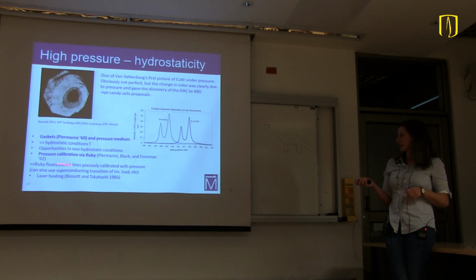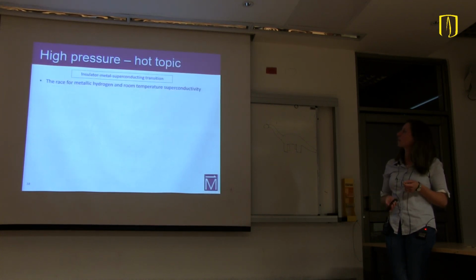And the next thing, also Piermarini and co-workers developed a way to measure the pressure inside the pressure cell by using the ruby fluorescence. So this is an example of a ruby fluorescence. When you shine a laser light on a ruby, it sends back fluorescence lines, and those lines are perfectly calibrated in pressure, so they shift in wavelength with pressure. So that was an absolute revolution for measuring the pressure.